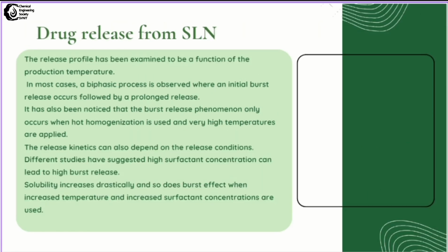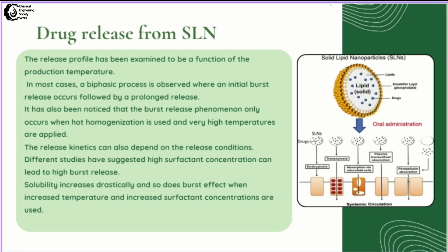Next up, we'll be covering drug release from SLN. It has been observed through intense investigations that the release profile is a function of the production temperature. For the burst phenomena, it has been observed that the release only occurs when hot homogenization is used and very high temperatures are applied.